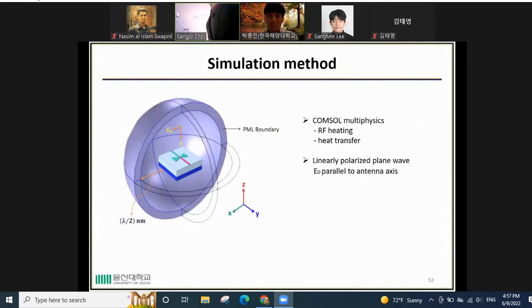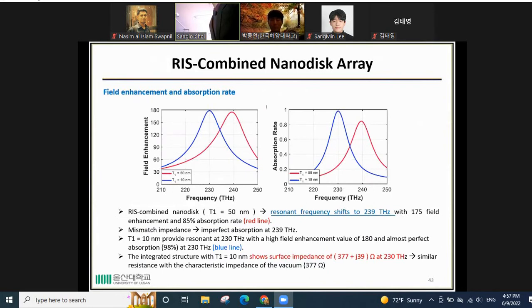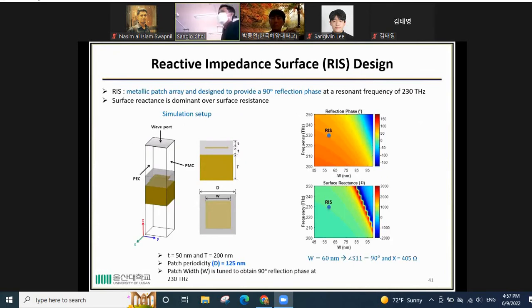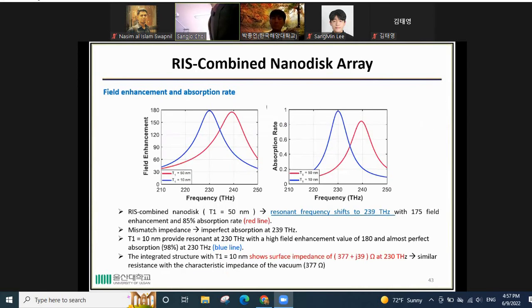So actually, the artificial reactive surface. We use the reactive surface to achieve high field enhancement and absorption rate for the circular patch. Actually, the reactive surface has a surface reactance characteristic. So this is the reactive surface, and this is the surface reactance. This surface reactance can cancel, or balance, the capacitance at 230 terahertz. Because as we combine the surface reactance, this is the combination between the antenna, the circular patch, and the 50 nanometer spacer, the resonance frequency moved to 239 terahertz.